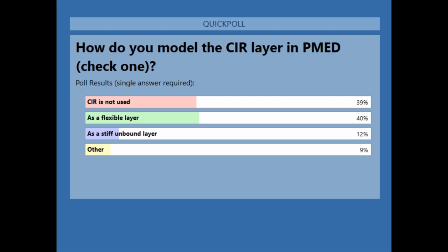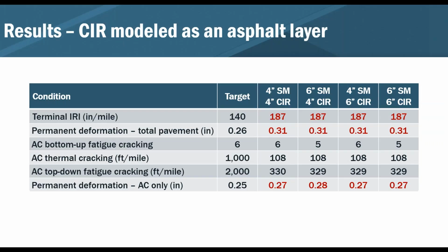We do have CIR properties from Virginia, and so we'll just leave that as is and go straight to the results. And so here you can see that as far as IRI goes, it really didn't matter, which again, I didn't expect it to, whether you put in a 4-inch surface mix or a 6-inch, or if you did a 4-inch CIR or a 6-inch CIR. Again, I don't think that's surprising to anybody. The same with the permanent deformation. The rutting is not terrible, even though it doesn't officially pass the reliability check. I would call that good. It's only 0.05 of an inch difference. So in my book, that would be close enough. And you can see the bottom up fatigue is all looking great. Thermal cracking is not an issue. Top down cracking is not an issue. Again, permanent deformation, you do see that it's mostly in the asphalt layer.